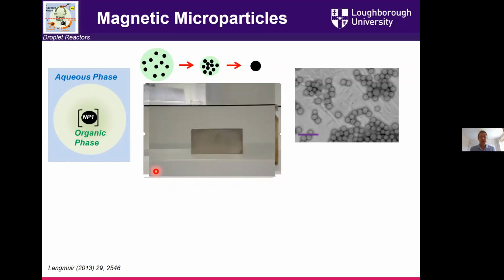Can't play the video, but the idea is that you can apply a simple handheld magnet and extract from some solution. And so in Dublin, we were playing around with emulsion droplets, where you would load those emulsion droplets up with iron oxide nanomaterials. Those emulsion droplets would be left to evaporate, they would condense down, and you'd be left with a condensed core of iron oxide nanoparticles that would respond externally to an applied magnetic field.